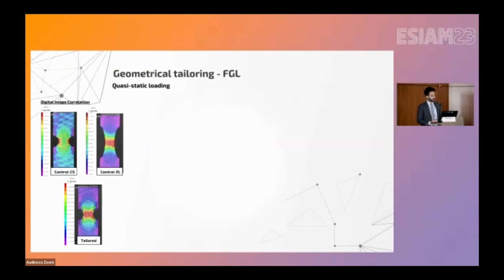So what we wanted with this technique was to get as far as possible from this localized nature, to more of a global load transfer. If you compare the pictures that I'm showing here, the controlled specimen and the tailored one, you can see that the distribution is quite similar.